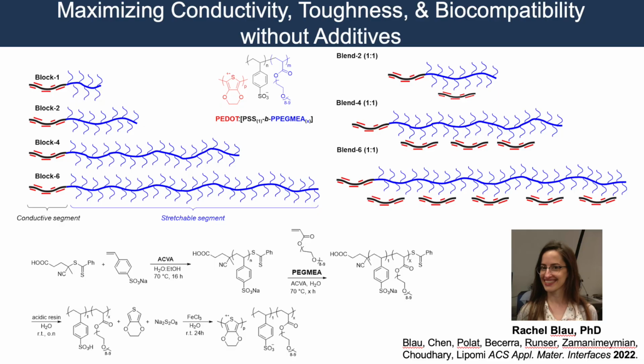These materials were not quite good enough for our purposes. They still, in some cases, produced some electrochemical effects. They were not the most conformable to the skin. So my postdoc, Rachel Blau, who's on the job market right now, actually made these materials where we used a much longer bottle brush segment to really increase the mechanical compliance of these materials. And we also synthesized these little extra segments of the conductive P-dot part.